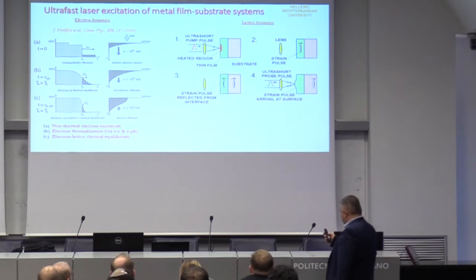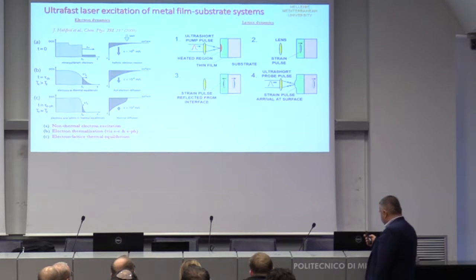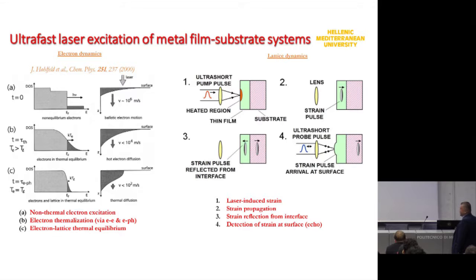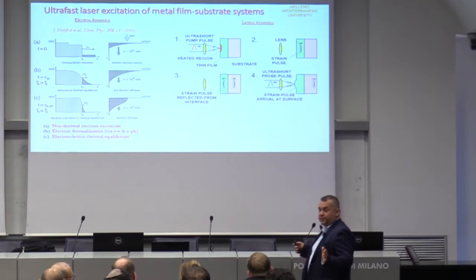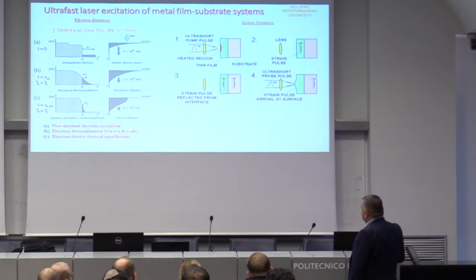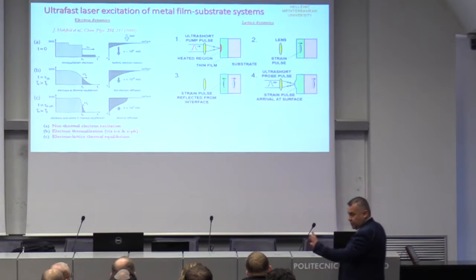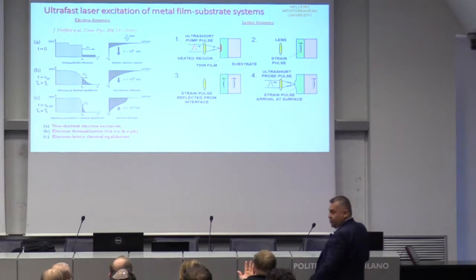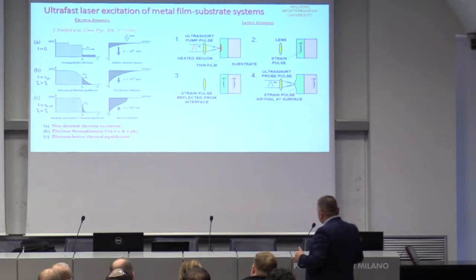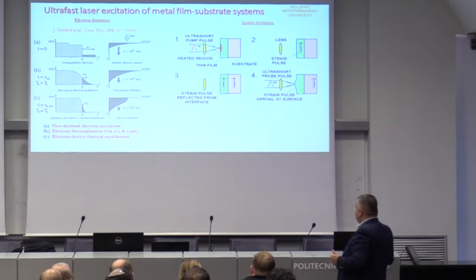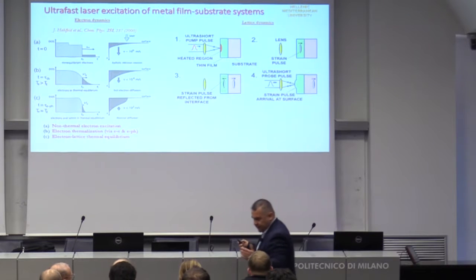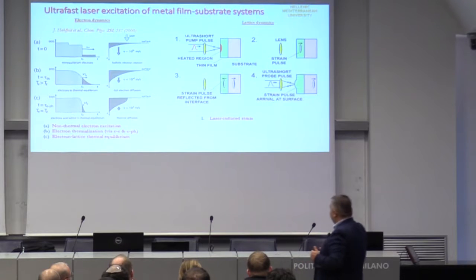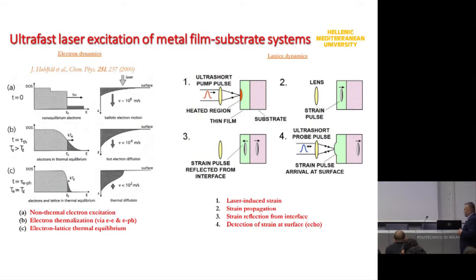So what is the lattice dynamics? Here is a very nice thing where we illuminate the laser beam in a very small volume where we increase the temperature of the lattice, as I showed you before, and there is a strain that goes outwards from the interaction region, and some of these strains go inside the material. So imagine that there is, for example, a thin metallic film and a substrate where we want to measure. The strain propagates inside the material, and when it reaches an interface between the two materials, there is an echo going back, and a traveling wave travels through the second material. Then we can come with a delayed probe pulse illuminating the surface and measuring, for example, the difference in reflectivity when the echo arrives on the surface. So these are the laser-induced strain, the strain propagation, the strain reflection from the interface, and the detection of strain at the surface.